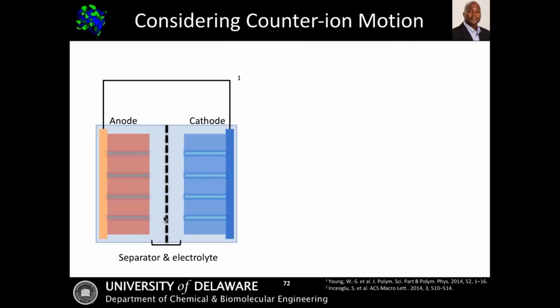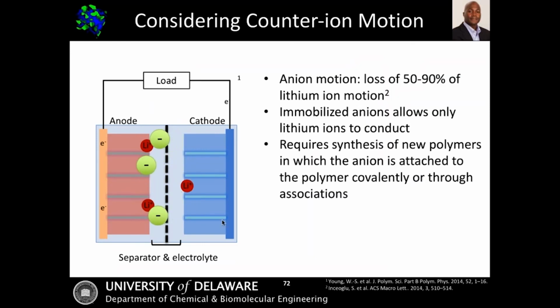So one of the things I want to mention is that these systems are great. We've doped in a salt, so we have an anion and a cation, but there are some potential issues. And one of those potential issues is that I need to consider my counter-ion motion. In this particular case, I can get ion pairs or ion triplets, for example, such that most of my lithium is either bound and doesn't move, or I get countercurrent flow of the anions. And all that's going to do is reduce the performance of my material and also potentially lead to charge polarization.